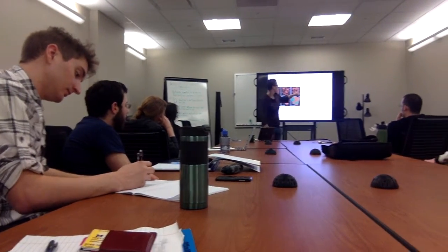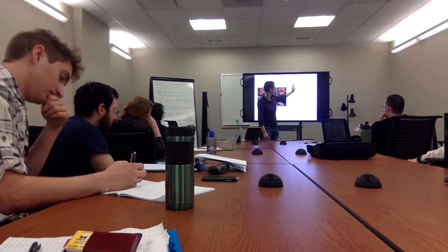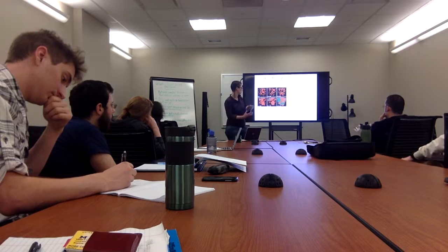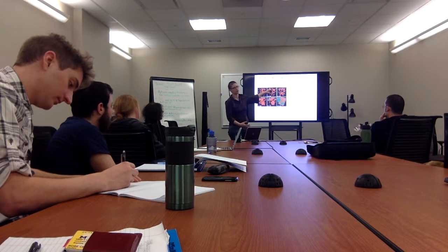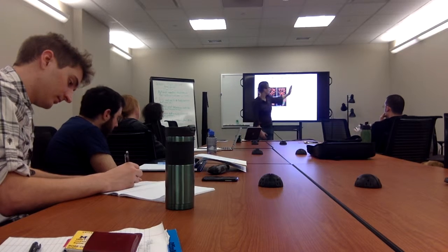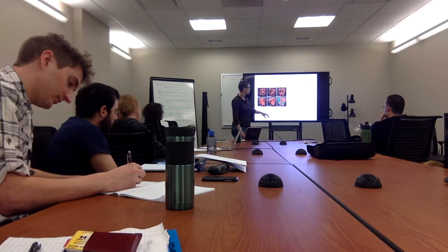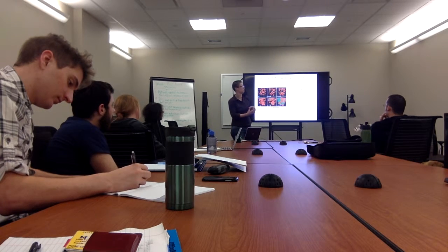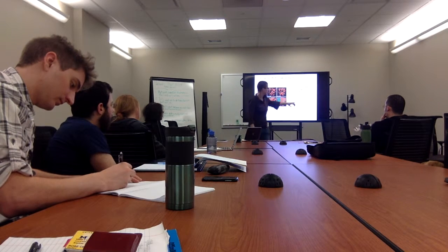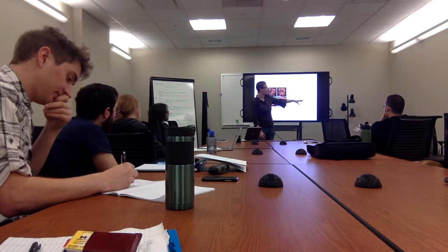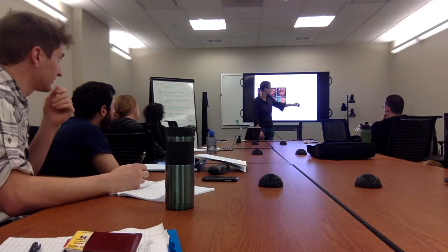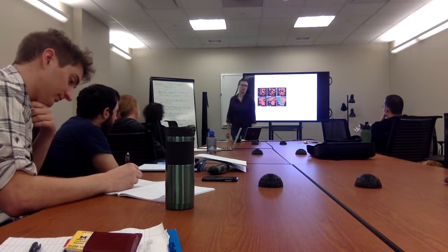What they're looking at is regions where the order parameter would pick something up if they set the cutoff very relaxed. And they found that if they tracked, so each color is a different density, how many nuclei they counted over time, then how many of these clusters that are pre-critical clusters they counted over time, they were able to use that to estimate what the nucleation rate would be, assuming that the nucleation rate from the pre-nucleation clusters was consistent, and they actually came up with values for nucleation rates that were close, that over-predicted experimental results for spheres, but came a lot closer than simulation results that have been done, which I thought was pretty interesting.